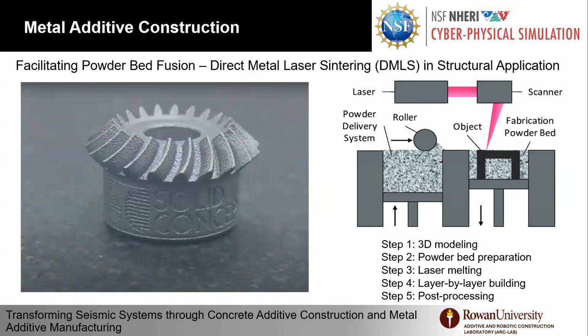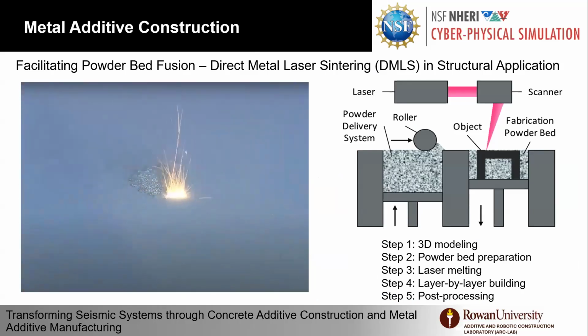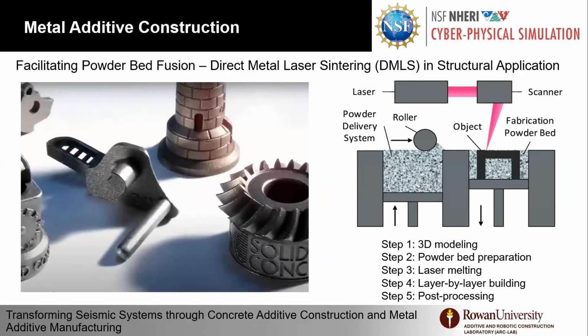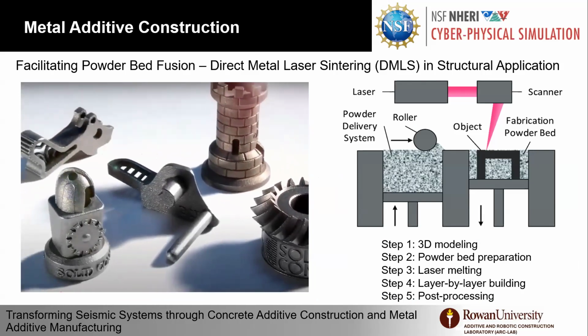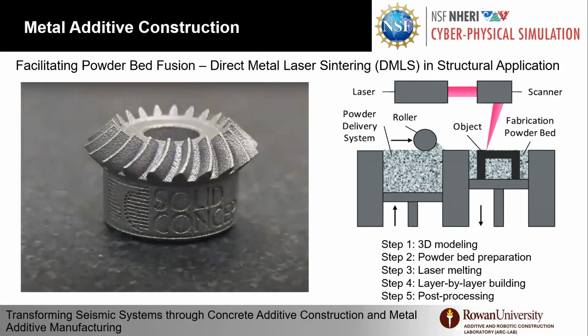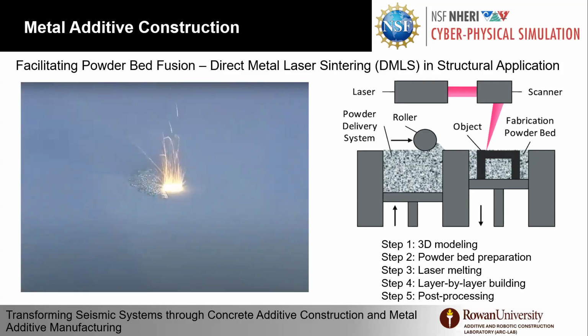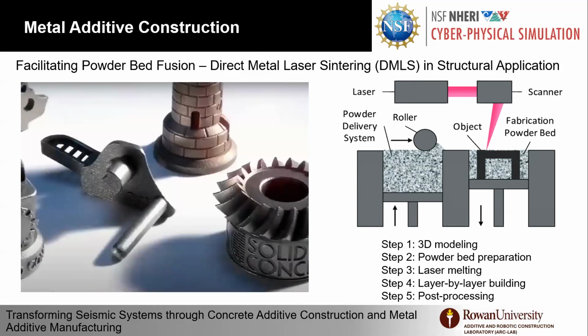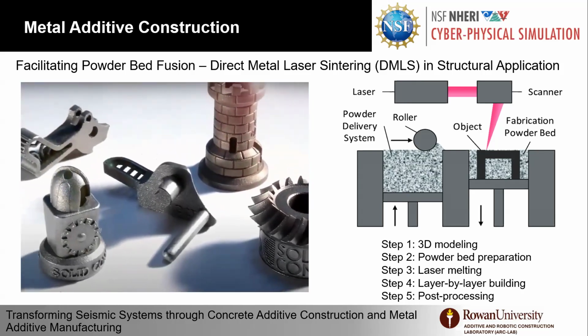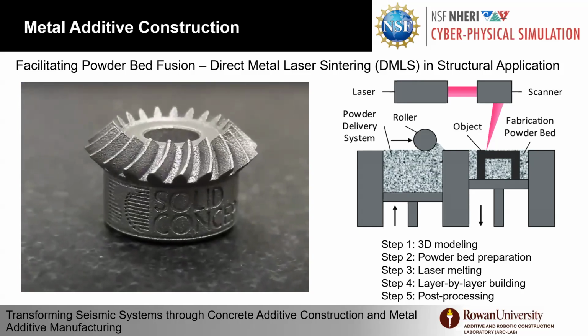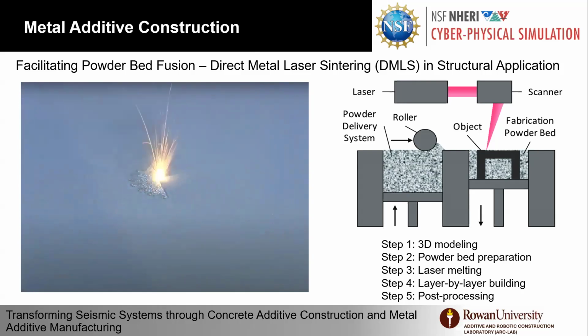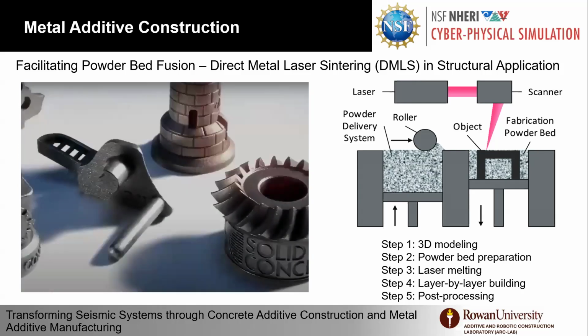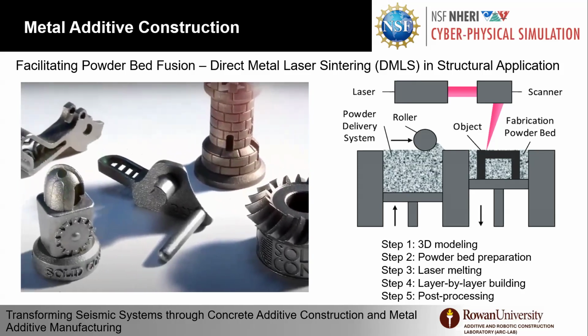However, in our lab, we try to facilitate powder bed fusion, with the technique called direct metal laser sintering, in a structural application. As you can see on the video on the left side, we can create objects using metal powders and a laser to sinter the layer as we intend. An object is melting or sintering inside the printer, and you can keep building the structure layer upon layer. The big challenge in this technique is the build volume. The printers are limited in size. Even now there is a lot of advancement. I was able to discuss with a company that now we are able to print objects like 5 feet by 5 feet by 5 feet.